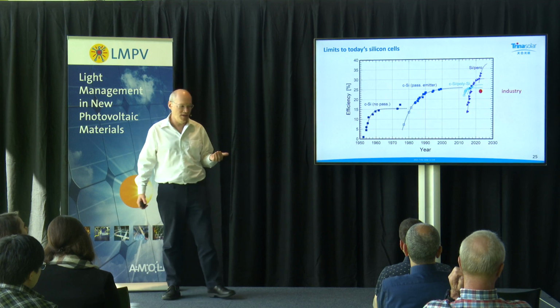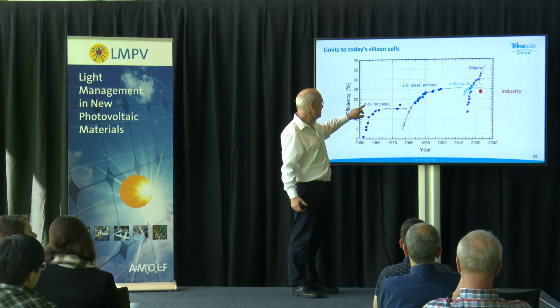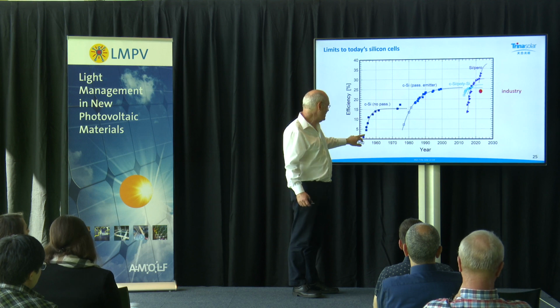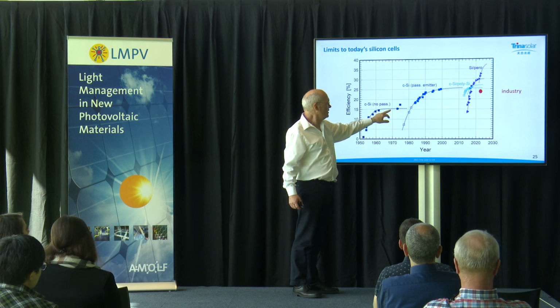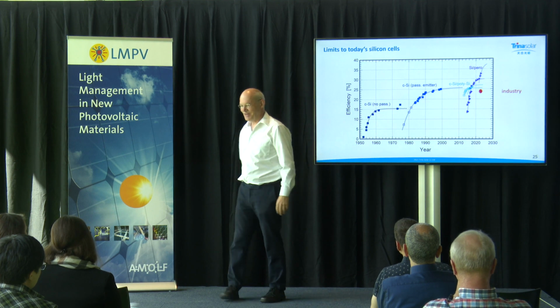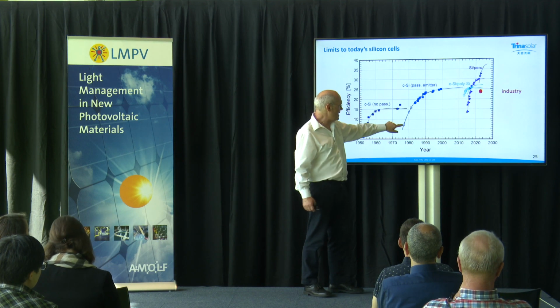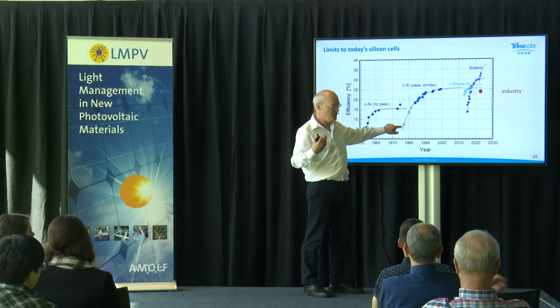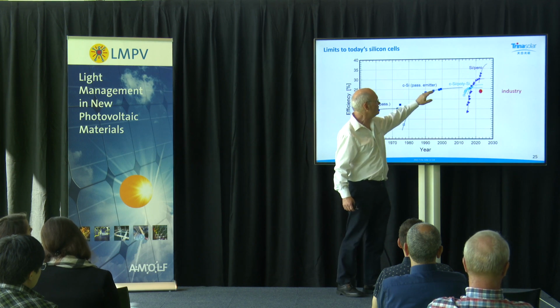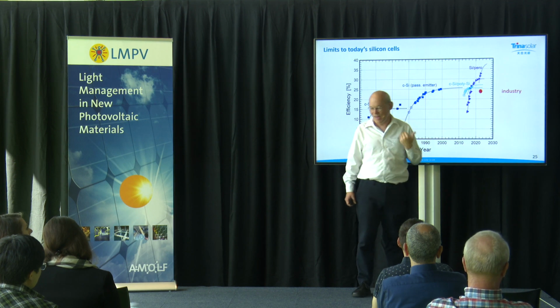Now the VOC is very high for perovskite cells, of course, but when you look at the past of crystalline silicon solar cells, first they had no passivation. It's like perovskite, you had no passivation for a while. It tapered off, and it actually took 20 years till people saw, wow, we should passivate our solar cells. These are all world records, but the empty symbols are internal results. And then only with passivating the emitter we got higher, till we tapered off around 2000, and then comes the passivating contact.